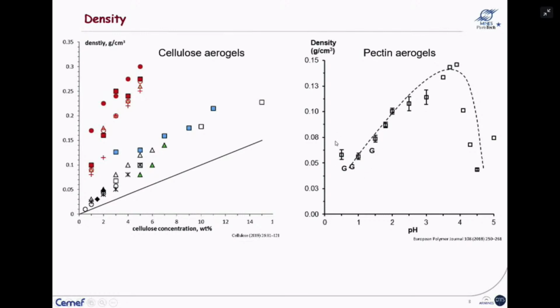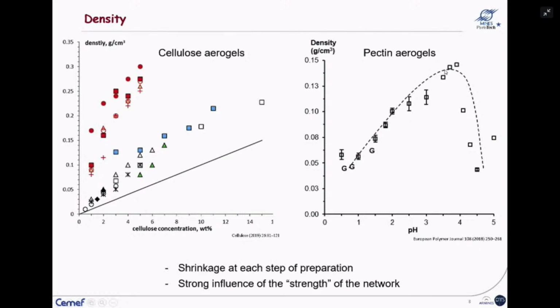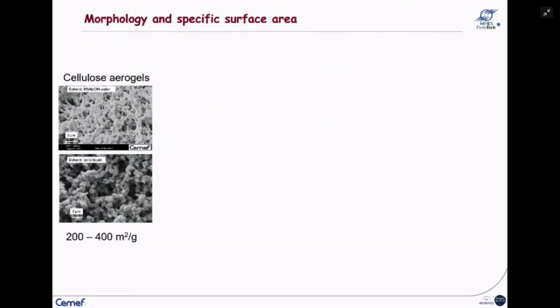So these are the gels that were then put in non-solvent and dried. And these are the solutions. So there was no gelation here. And you see that the sample is contracting, and that is why the density can vary a lot. So the message to take is that there is a shrinkage or contraction at each step of the preparation, and there is a strong influence of the strength, sort of a strength of the network before making the solvent exchange and before drying.